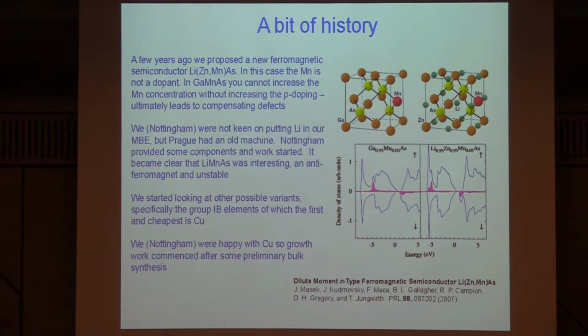And looking at the band structure modeling, which was done by my colleagues in Prague, you can see that it's almost identical to the band structure of gallium arsenide, same band gap. It's amazing. So this looked like a really, really promising material. Now, lithium's not very nice in MBE machines, and I didn't really want to put lithium in, or zinc for that matter, into my production machine.